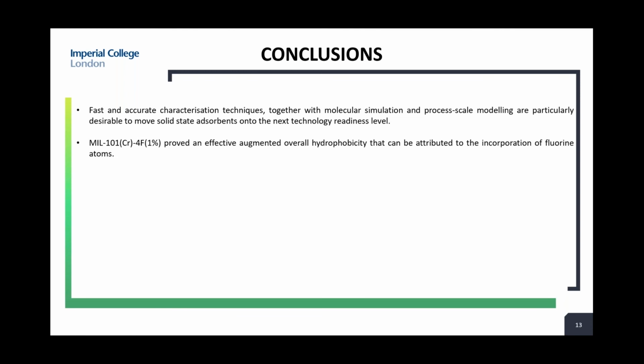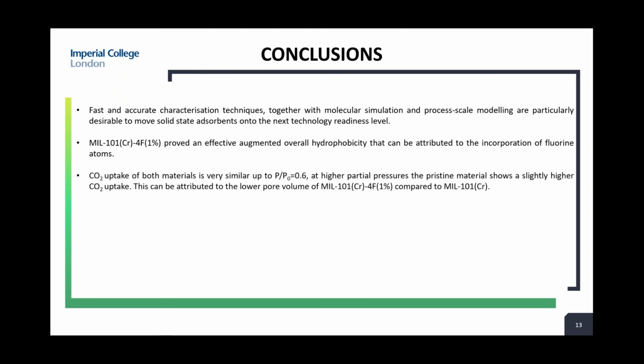So the fluorinated MIL-101 proved to have an augmented overall hydrophobicity that was attributed to the incorporation of fluorine atoms. And the CO2 uptake of both materials was pretty similar up to a partial pressure of 0.6. However, at higher partial pressures, the non-modified material showed a slightly higher CO2 uptake, attributed to the lower pore volume of the functionalized material.